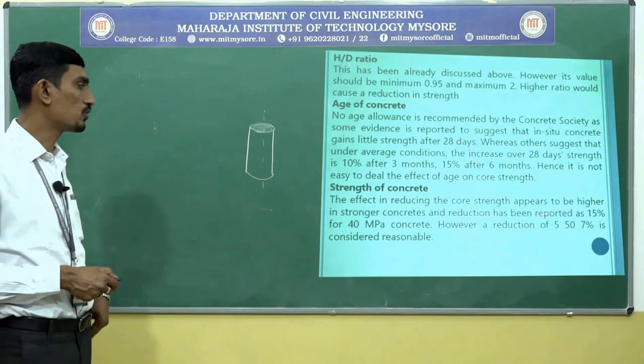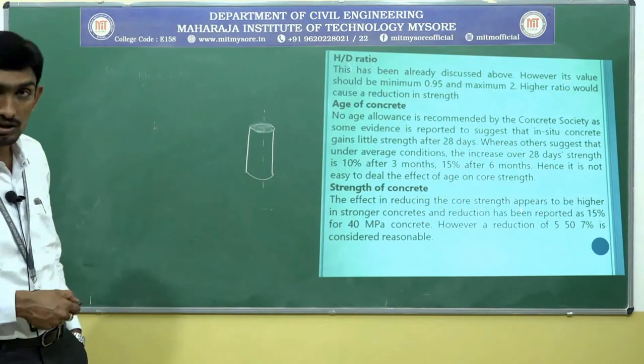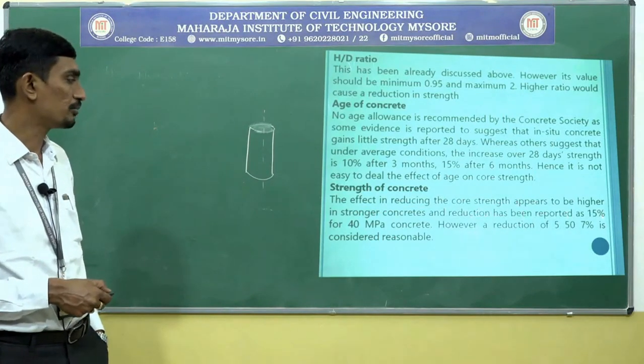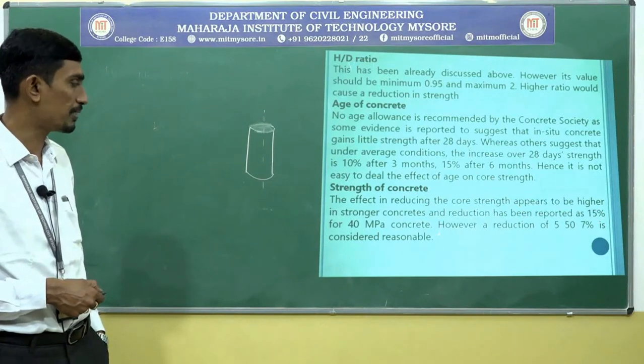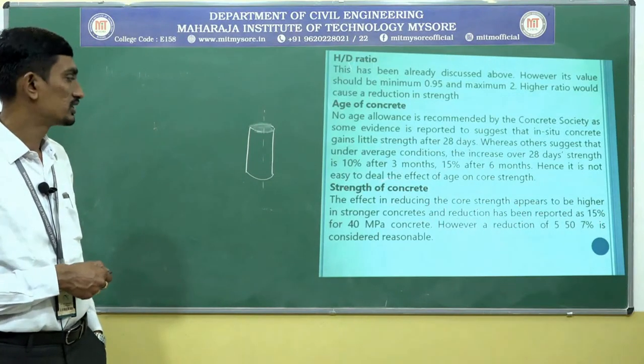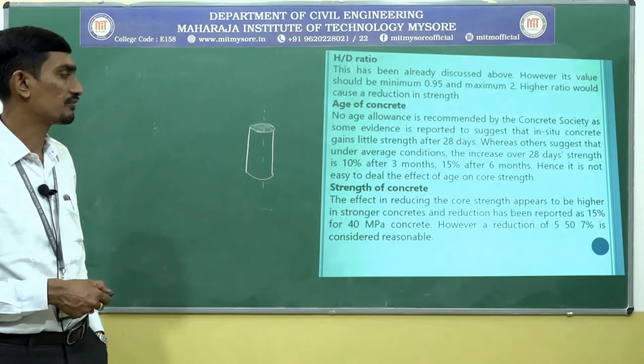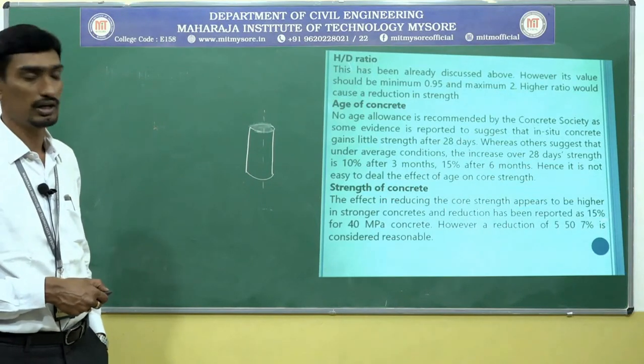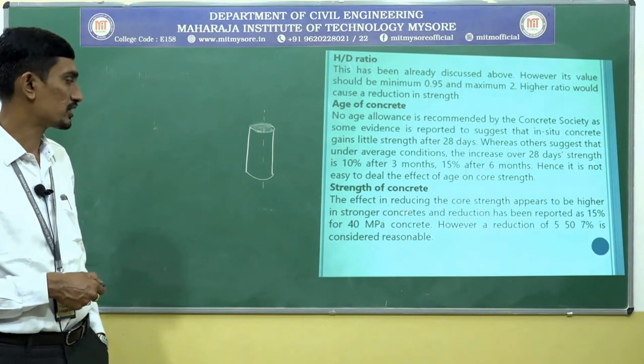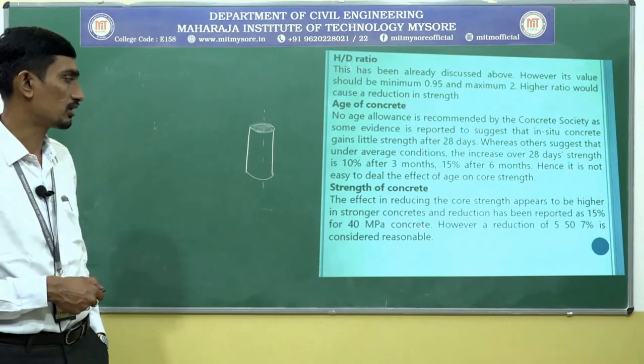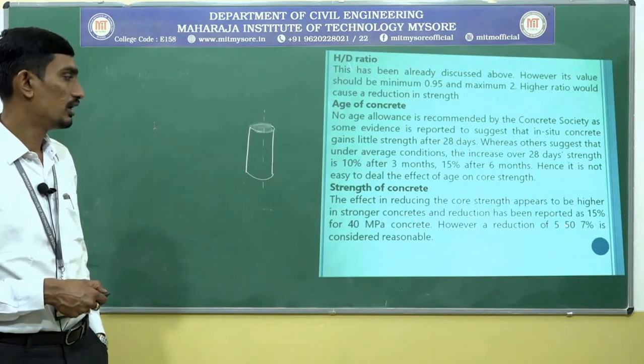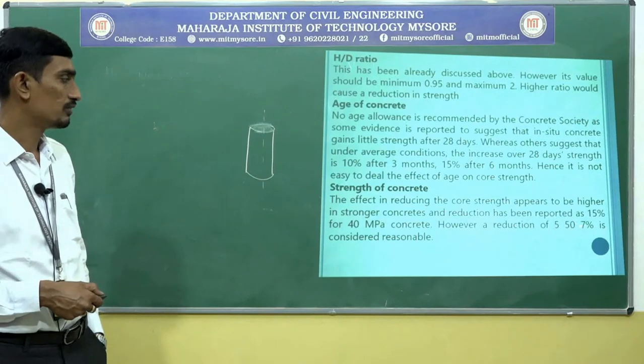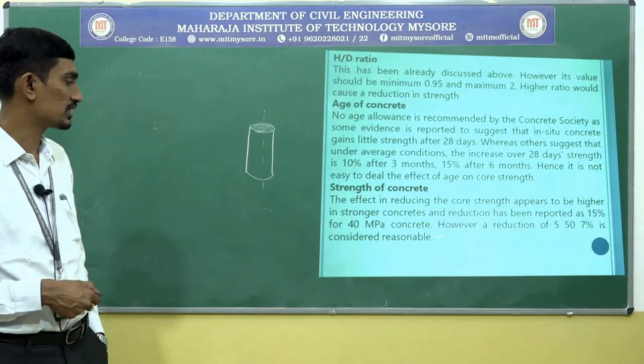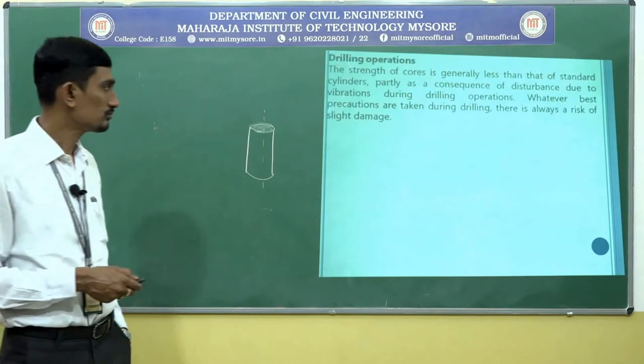The effect in reducing the core strength appears to be higher in stronger concrete, and the reduction has been reported as 15% for 40 megapascal concrete. That means this strength reduction will be more in the case of high strength concrete. You can see a 15% reduction will be there in the case of 40 MPa concrete. However, the reduction can be 5 to 50%, and 5 to 7% is considered reasonable.